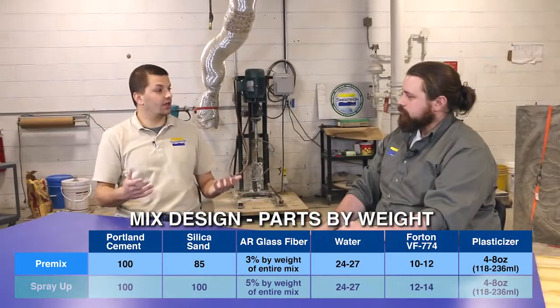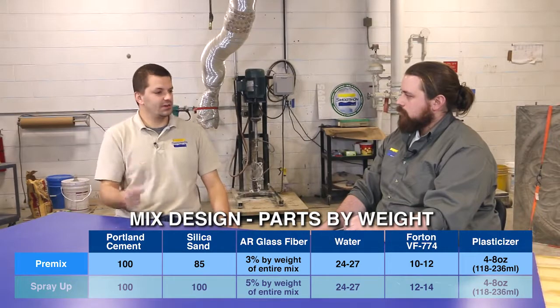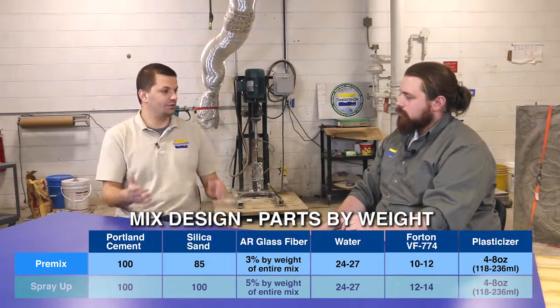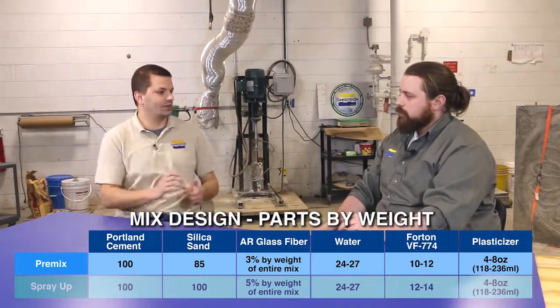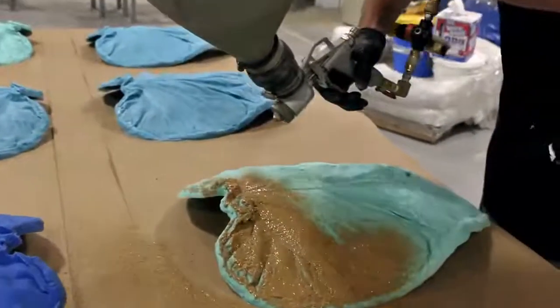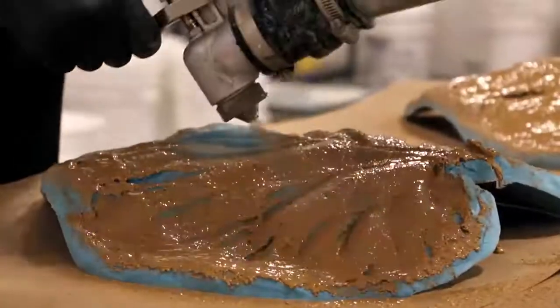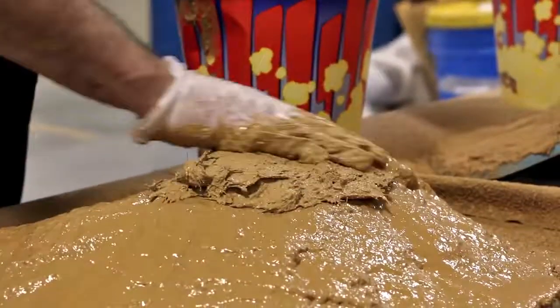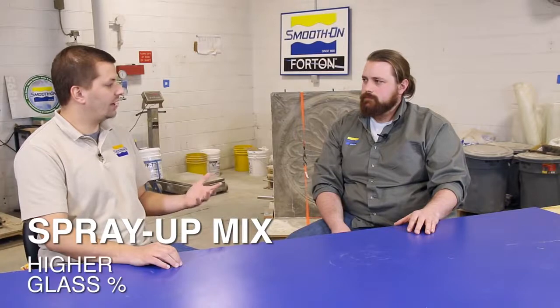The premix, like you said, is a very common mix design that a lot of people use. The misconception is that it can still be sprayed, and that's where we have the confusion of spray up and premix. Right. The premix is sprayed through a hopper gun, generally on a smaller application, and then the backer mix is applied generally by hand. So the face coat, in almost all circumstances, is going to be sprayed. That's the best way to do it. So that's where the confusion is. If it's sprayed no matter what for a face coat, you might think, well, I should go with the spray up mix design, but actually, if you're using a hopper gun and then mixing the fiber in for the backup mix, you probably want to go with the premix. So yeah, now that we're talking about the backer mix, with the spray up, you get a higher glass percentage.